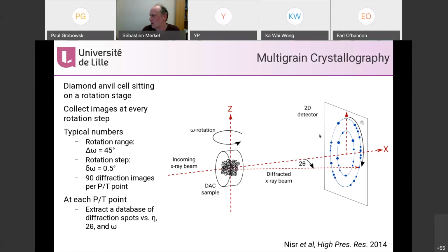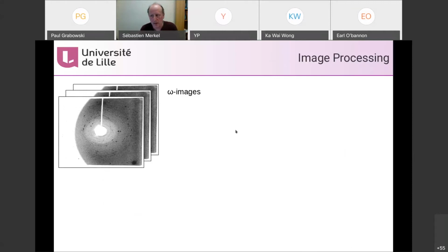And then you look at the spots. All those spots you get because your sample has grains and it's very spotty. It's common in diamond cell experiments that the diffraction images are spotty. But here we actually extract them one by one. And so we get a database of spots we measure as a function of angles: the eta angle, the azimuthal angle on the detector, the theta diffraction angle, and the omega rotation at which we saw the diffraction spots.